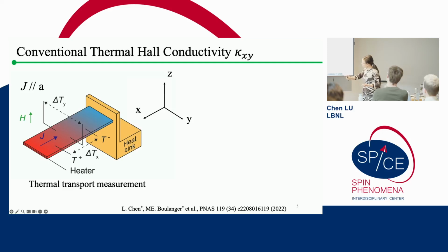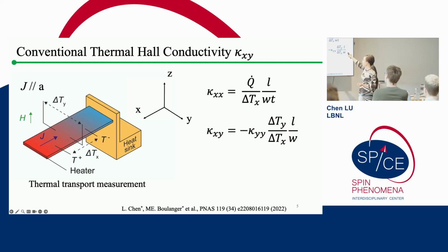The thermal gradient along the x direction can be measured by two thermometers, the so-called T plus and T minus here. With this so-called delta Tx, you can calculate the longitudinal thermal conductivity. But in a material that actually has a non-zero thermal Hall effect, when you apply a magnetic field perpendicular to the sample plane, you get a non-zero transverse temperature gradient, the so-called delta Ty here.